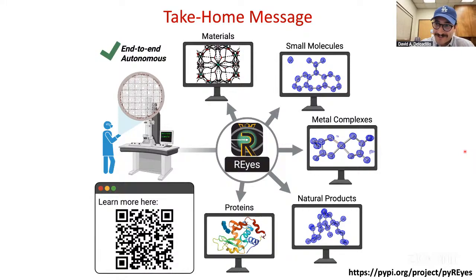Yeah, it's a great question. I think you're spot on. This is very heavily biased towards the solvent that you're using and those samples that have a high propensity for crystallization, right? We have gone through and tested different solvents, going through a traditional crystallization screening where you have ethanol, water, acetonitrile, THF, ethyl acetate, etc. And you do end up pulling out different samples depending on your solvent. So it is kind of brute force, especially when you get something so heterogeneous like that. But the more you get towards a pure sample or less heterogeneous, the more that you can pull out, essentially.